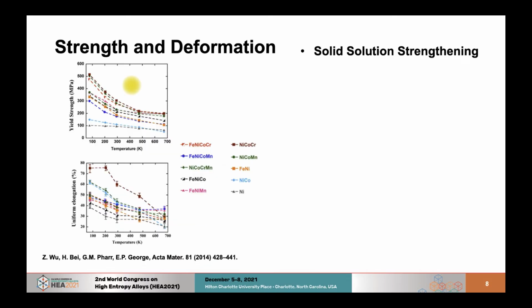And regarding solid solution strengthening, so the sigma zero term, that trend I just showed can be well explained by Varvenne's model. So this is Wu's work that I mentioned, that was the first study to really report these compositions. They show that chrome cobalt nickel alloys are stronger and do display a better ductility than other Cantor alloy derived equiatomic compositions, as shown on these two curves.